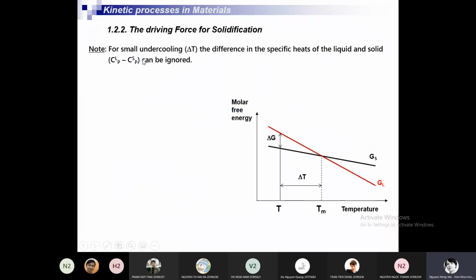So we have to note that for small undercooling, if the delta T is small, the difference in specific heat can be ignored. So we can say that the specific heat of the liquid and solid are the same, are equal, if the undercooling is small. Okay. So in this case, delta S is approximately independent of temperature. Do not depend on the temperature.